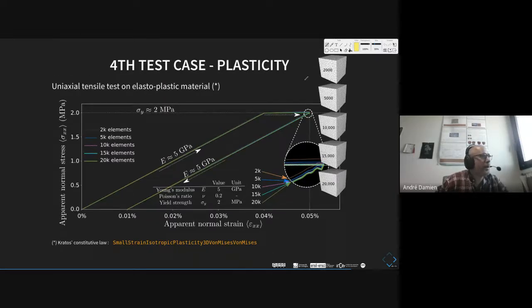Now, another test case is about plasticity. I'm not a specialist of plasticity, so I made a very simple test case. Here we test this sample with 2,000 discrete elements, 5,000, 10,000, 15,000, and 20,000, just to test if the plasticity is sensitive to the mesh size. And as you can see, this is not the case.